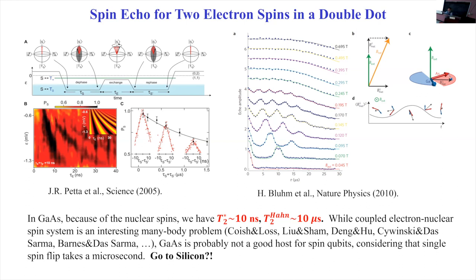Mostly the reason for that is because of the underlying nuclear spins. In gallium arsenide, you have three isotopes: gallium 69, 71, and arsenic 75. All three isotopes are spin three halves. So you have nuclear spins everywhere. The electron goes into that system, the conduction electron, you have an antibonding S state, which has finite probability at the nuclear site, so they have finite contact hyperfine contact, which the electron spin can see basically all the nuclear